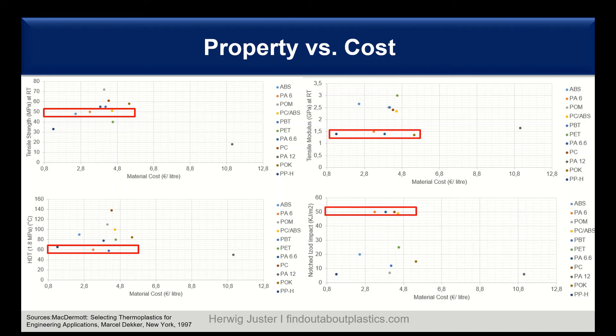And here the un-notched Izod impact — again the same: when I need a high un-notched Izod impact like 50 kilojoule per square meter, I have the most economical option in Polyamide 6, and the most expensive is PC/ABS. So this is a really useful tool to graphically analyze the cost situation.